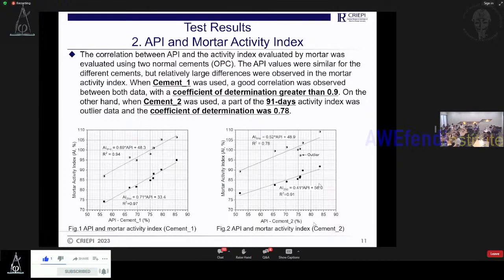The next figure shows the relationship between API and mortar activity index. The left figure shows the result from using cement 1, and the right one shows the result from using cement 2. As shown in the last figure, there is no difference in API between cement 1 and cement 2. But on the vertical axis, the activity index shows a little bit of difference between those two cements.